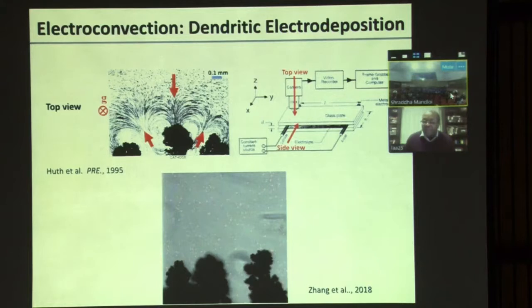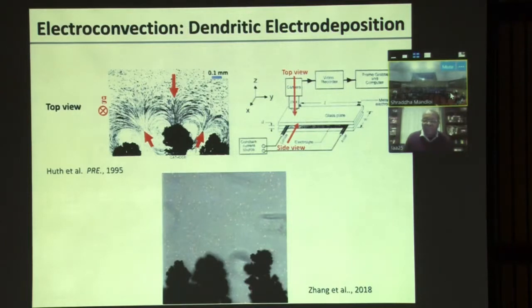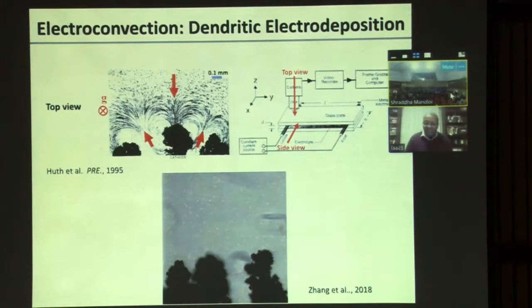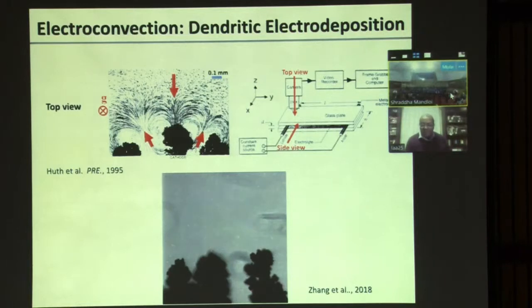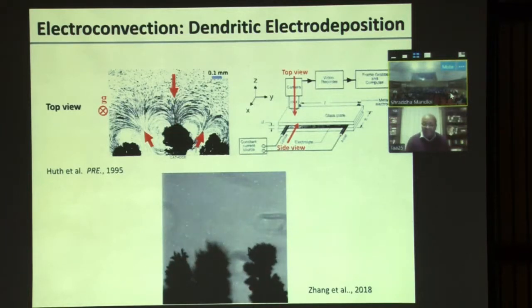Some evidence that this connection is reasonable comes from relatively old work by Huth et al., which showed in deposition of copper under an optical microscope essentially exactly what I described—structures growing from the surface of the electrode fed by flow lines bringing material selectively to the tips. A video from my group measured a few weeks ago using fluorescent tracer particles shows more or less exactly the same thing: fluid motion in a system that's supposed to be closed and stagnant, and that fluid motion is feeding the growth of the morphological instability known as dendrites.